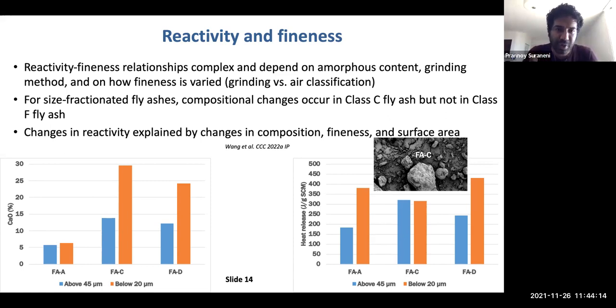So there is a concentration of calcium oxide in the, not calcium oxide, but phases bearing calcium oxide, really. But calcium bearing phases are concentrated in the fine fraction. So when you talk about how the reactivity changes, you have to remember that the reactivity is changing because of fineness, but it's also changing because of compositional effects. So we actually measured the reactivity, and you have it here.